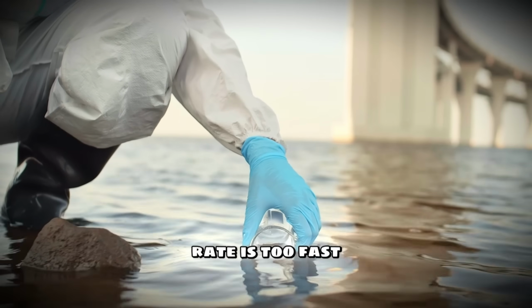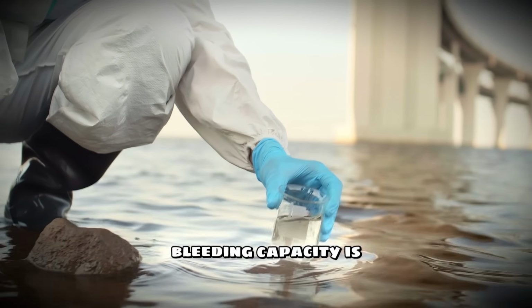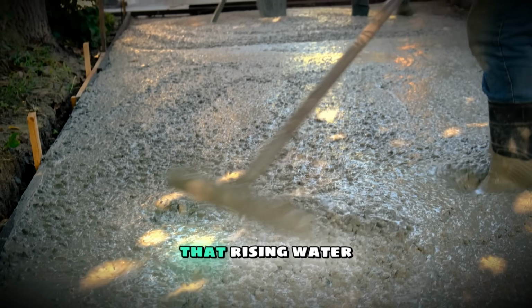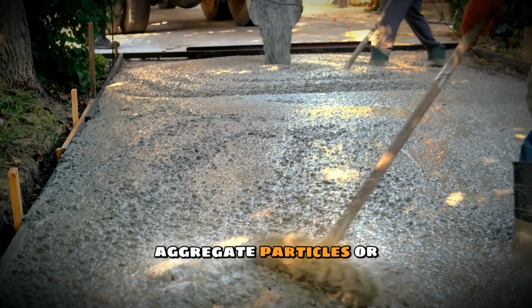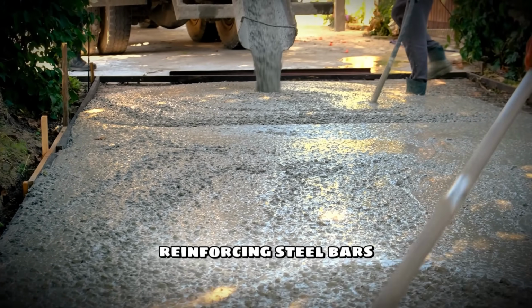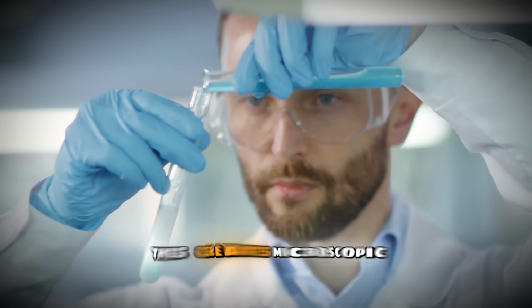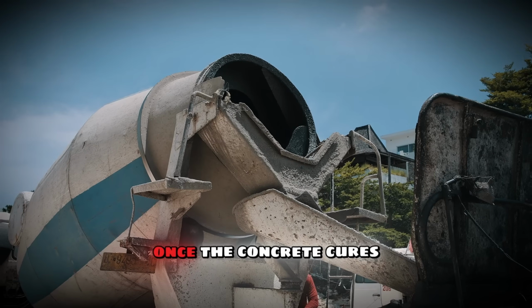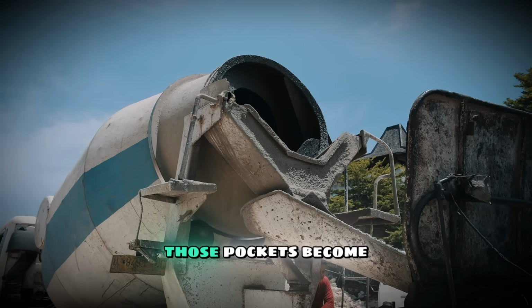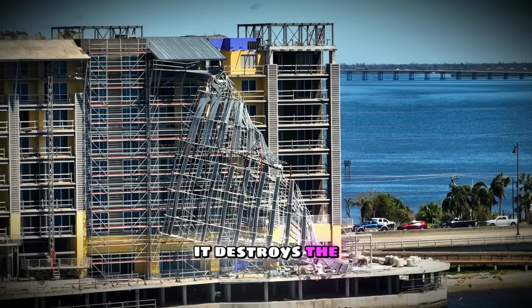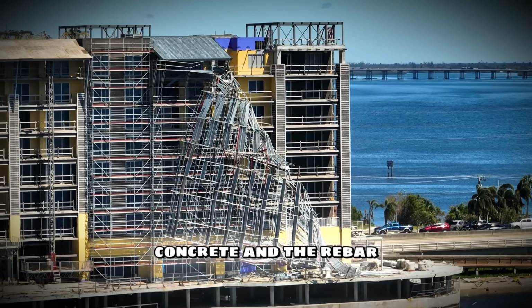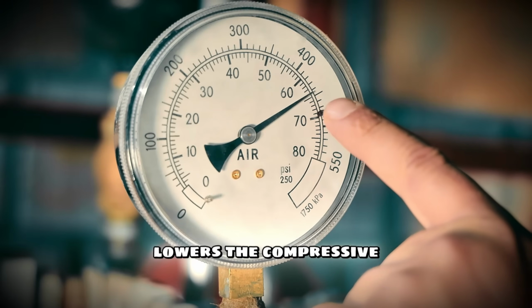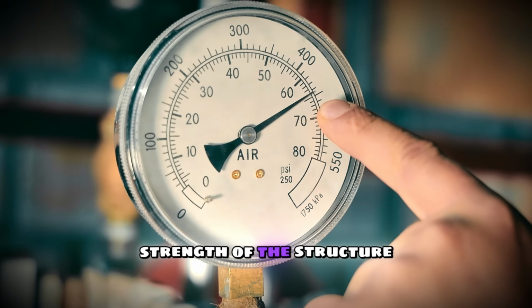If the bleeding rate is too fast, or the total bleeding capacity is too high, that rising water gets trapped under large aggregate particles or reinforcing steel bars. This creates microscopic voids and water pockets. Once the concrete cures, those pockets become permanent weak spots. It destroys the bond between the concrete and the rebar, and it significantly lowers the compressive strength of the structure.